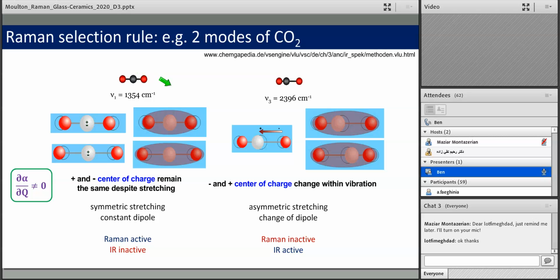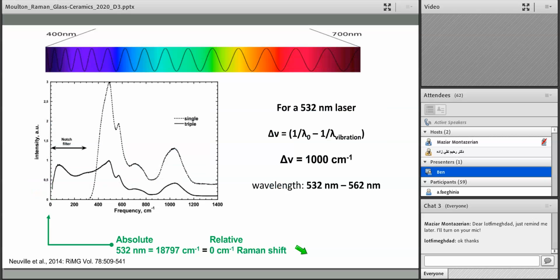And on the right-hand side, we see that the positive and negative charges are shifting with the vibration, but the same shift to the left or right gives the same size of the overall sphere. So there's no change in this quantity, and the coefficient here, delta alpha over delta Q, is constant, or is, sorry, zero. And so this mode will be Raman inactive, but it will be accessible by IR. And I won't get into too much detail with IR, except to say that we need a change in the polarizability with a change in the displacement of the atom to see the Raman spectrum.